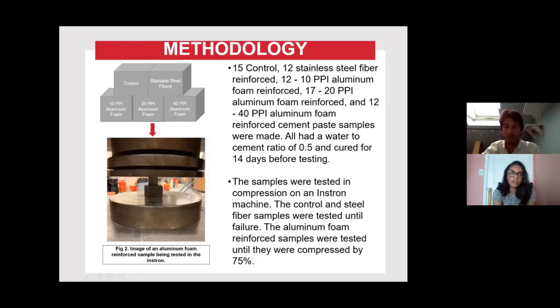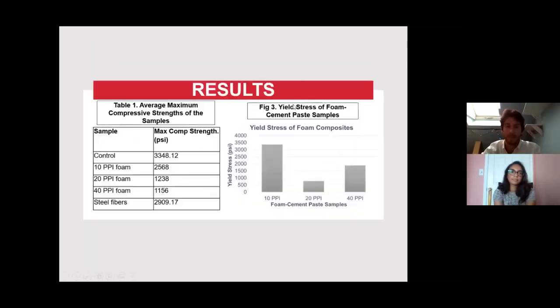The image on the left shows what the samples looked like when they were in the testing machine. The control and steel fiber samples were tested until failure, and the aluminum foam samples were tested until compressed by 75%. The results we gathered from this testing are graphed in these figures on the screen.